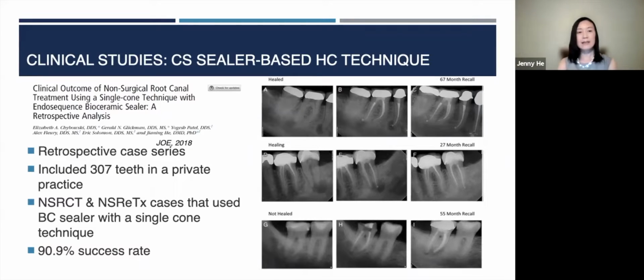So this paper we published back in 2018 is an outcome study on the BC-based hydraulic condensation technique. This was a retrospective case series that included over 300 cases treated in our private practice. It included both initial treatment and retreatment cases, both cases with pre-op lesions and cases without pre-op lesions. All these cases were obturated using BC with the hydraulic condensation technique, and all of those were treated in a single visit. We found the overall success rate was close to 91%, which is well within the success rate reported in the literature for these types of cases.